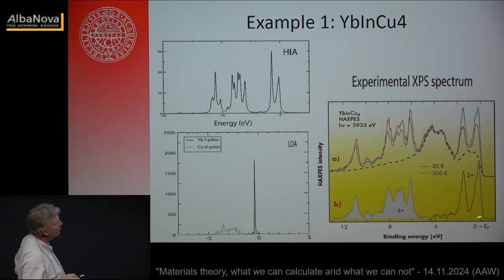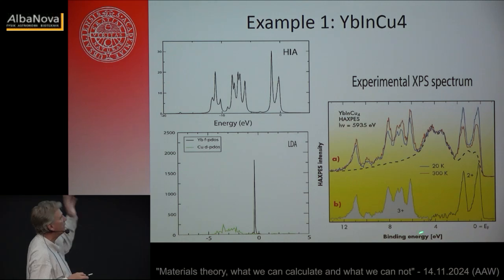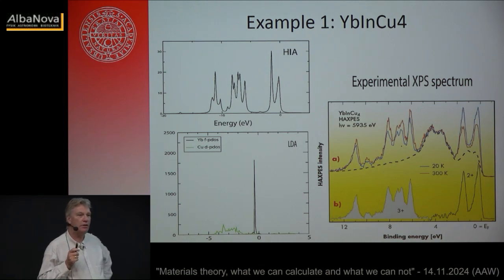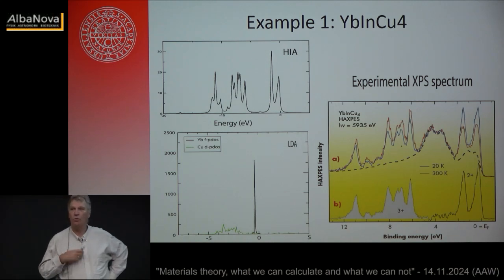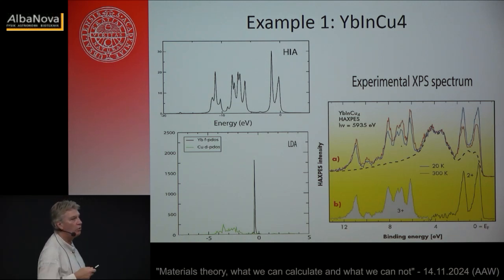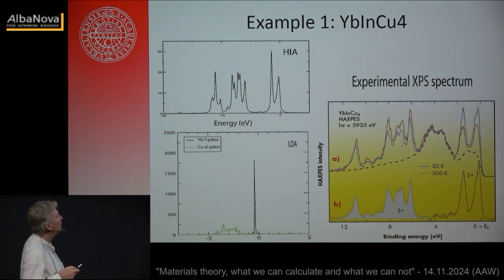So this is something that is occupied states, so the Fermi level is at 0, you don't see in photoemission anything that's unoccupied, and there are electron states that can be kicked out from this material with the binding energy down to almost 12 eV or so. If I now took the conventional DFT eigenvalues and pretended I ignored my own warning that I started this talk with, that there is not really anything I can compare to experimental data, I do that anyway. Then I get this narrow band here. So that's the 4f contribution from regular DFT calculations. So this agrees terribly with what's over here, right?